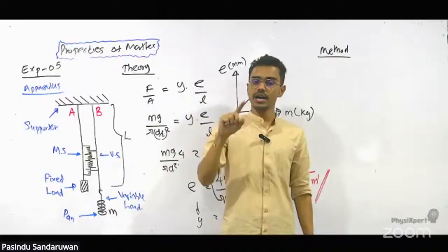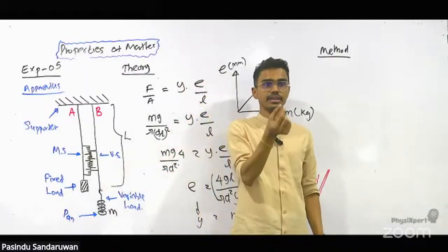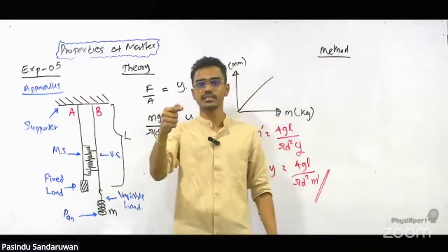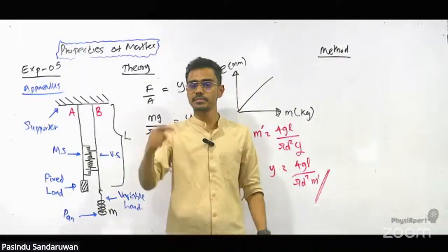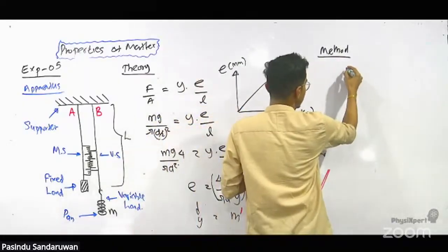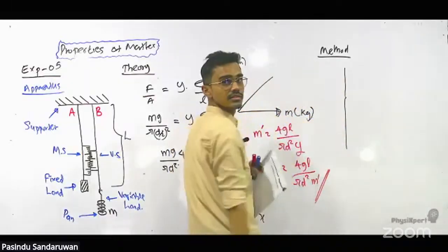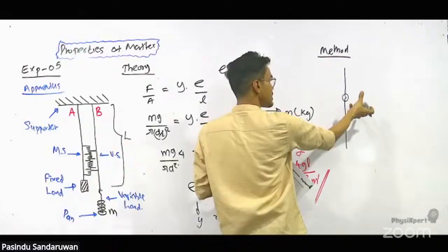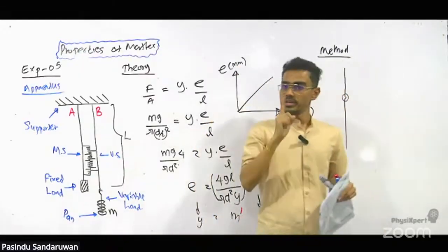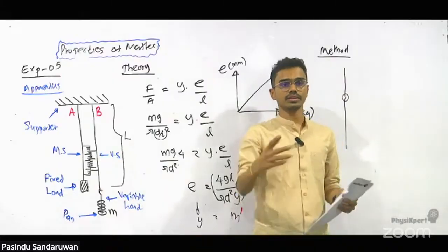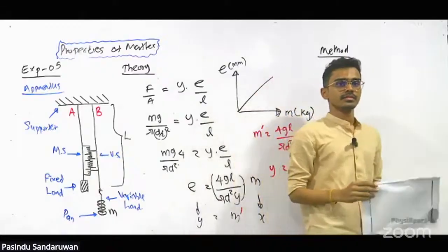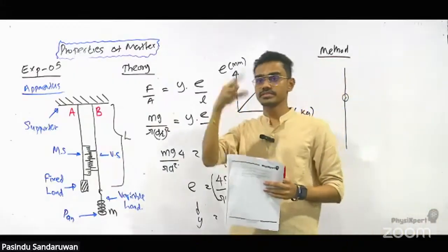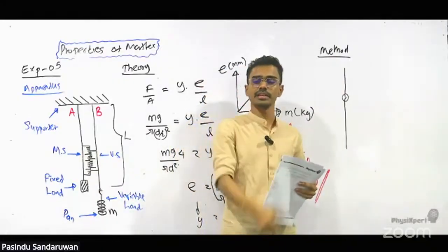If there are any bends in the wire, since this is a thin wire, sometimes when the load is applied the bends are stretched and become straight. To minimize such errors, we are unloading the system as well. When you unload, you may get a difference in the initial reading.